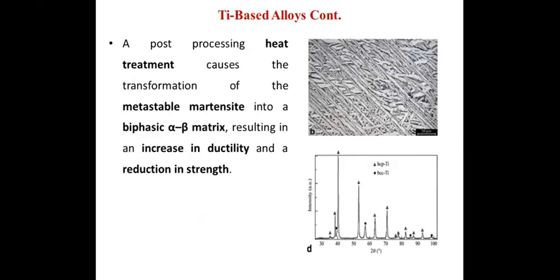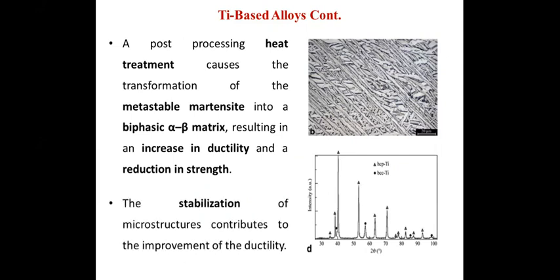To modify this ductility, heat treatment helps change the metastable martensite into a biphasic alpha-beta matrix, resulting in an increase in ductility and a reduction in strength. The stabilization of microstructures contributes to the improvement of the ductility.